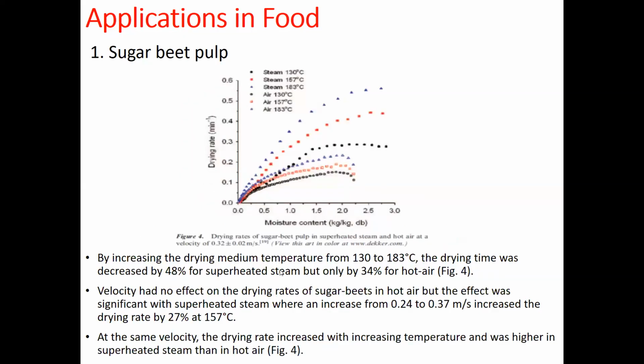By increasing the drying medium temperature from 130 to 183 degrees C, the drying time was decreased by 48% for superheated steam, but only by 34% in hot air drying. The velocity had no effect on the drying rate in hot air, but the effect was significant in superheated steam, where an increase from 0.2 to 0.3 increased the drying rate by 27%.